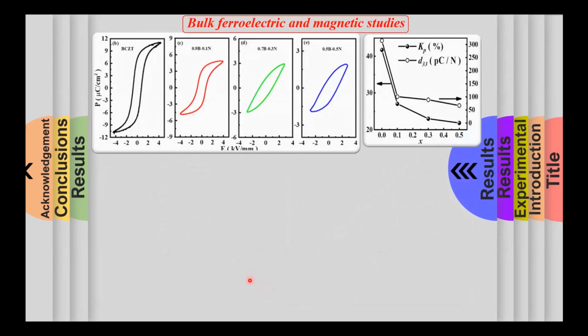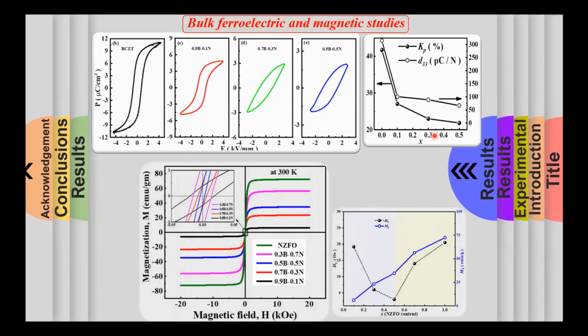Bulk ferroelectric and magnetic properties were also investigated. Composites with up to 50 weight percentage of nickel zinc ferrite exhibited the polarization versus electric field hysteresis loop, thereby confirming their ferroelectric nature. With increasing weight percentage of the magnetic phase, the saturation polarization decreases and the coercive field increased. Similarly, the electromechanical coupling factor and the piezoelectric charge coefficient showed a decreasing trend with increasing weight fraction of the nickel zinc ferrite magnetic phase.